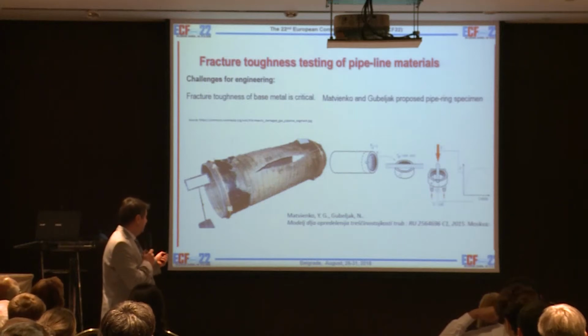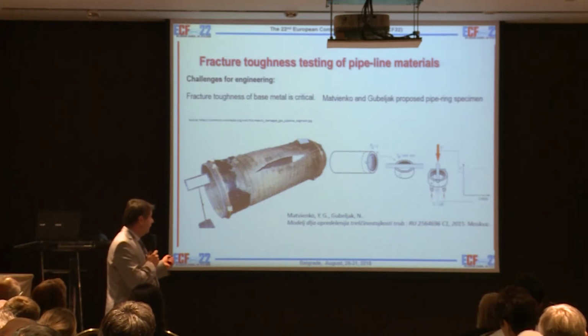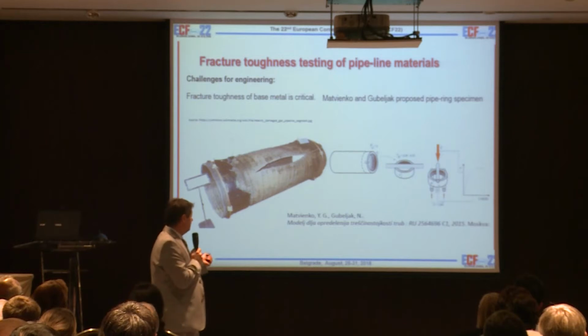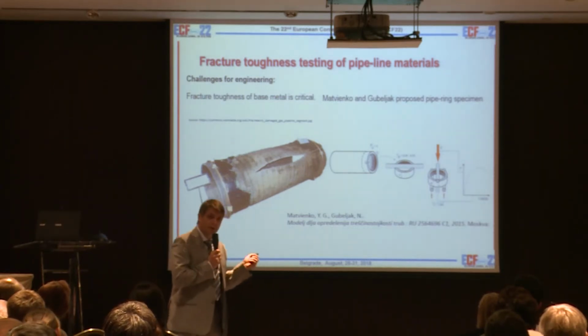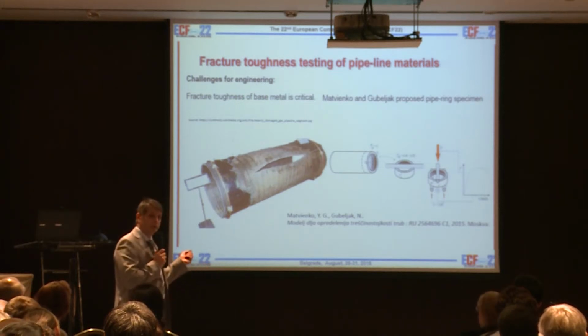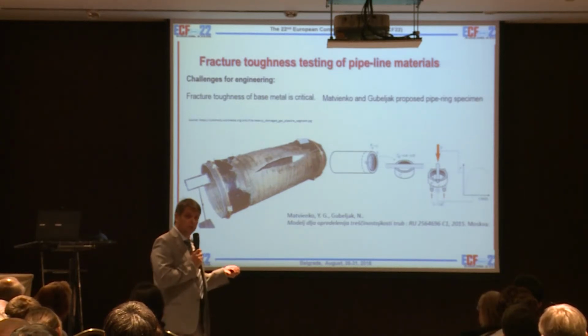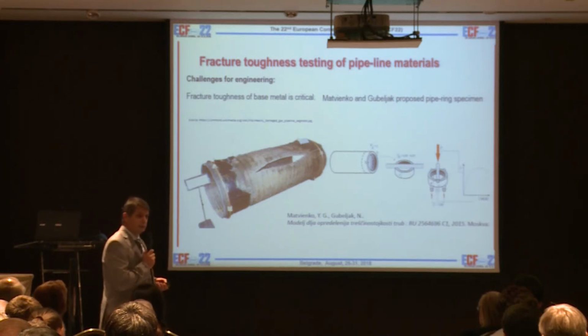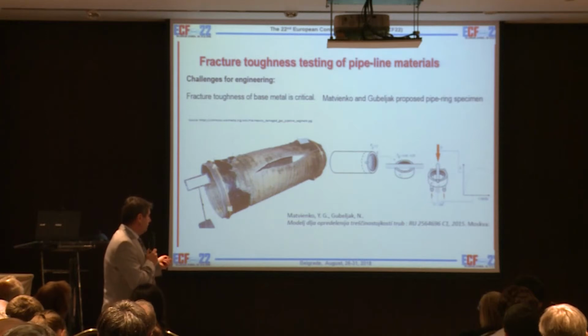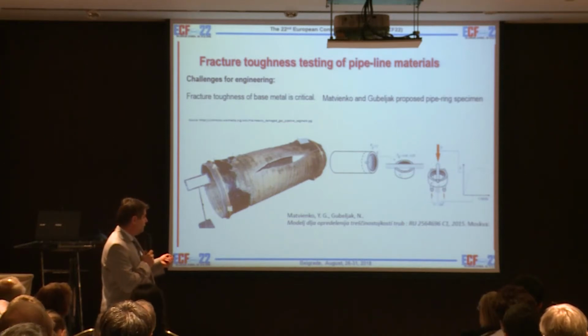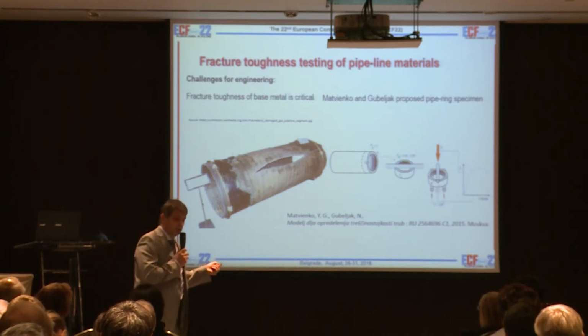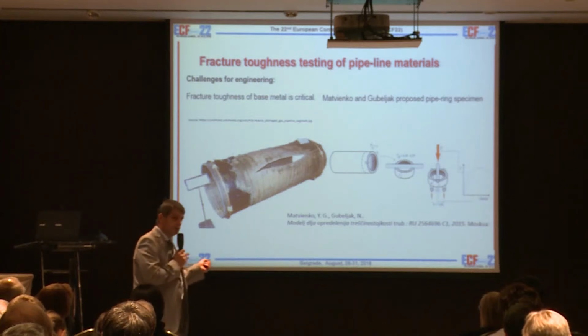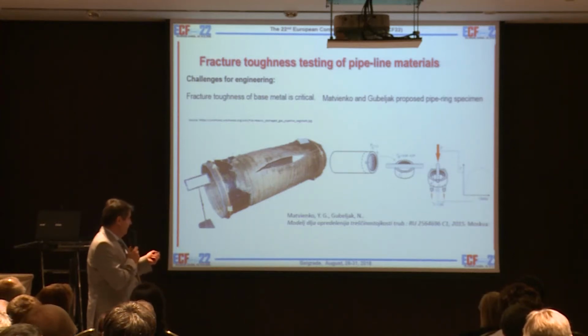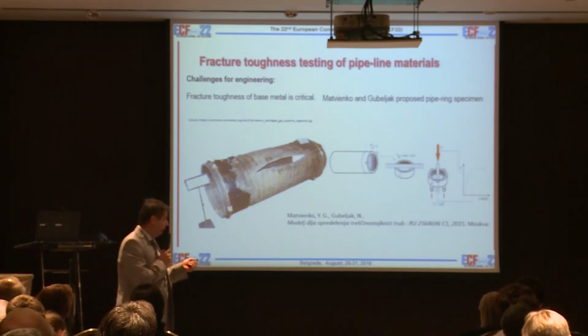Here you can see that an axial longitudinal crack is actually arrested on the pipe. It means that for this pipe we have enough toughness that the crack is arrested and the damage is only local. This is what we want to have if an accident happens, because the damage will be as small as possible. So this is the idea which was patented in Moscow, in Russia, sorry, with Professor Matvienko from the Russian Academy of Science, also one of our collaborators.